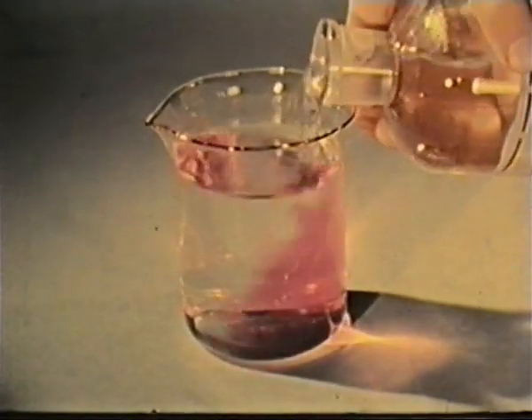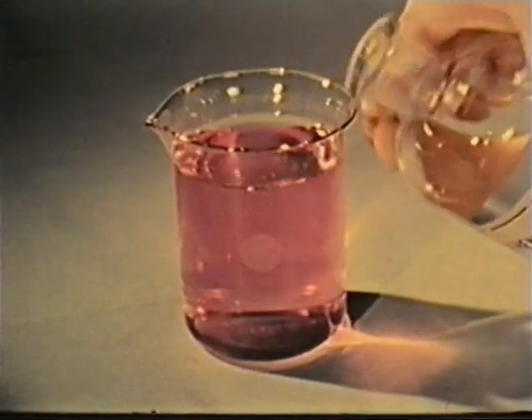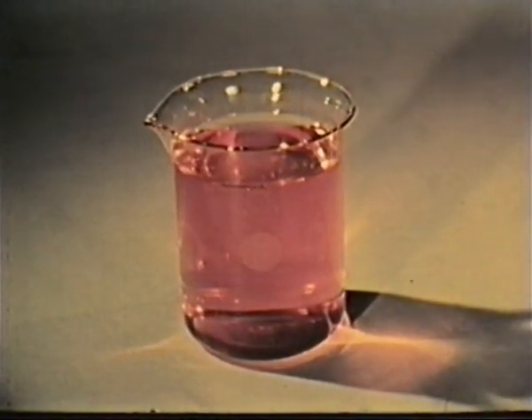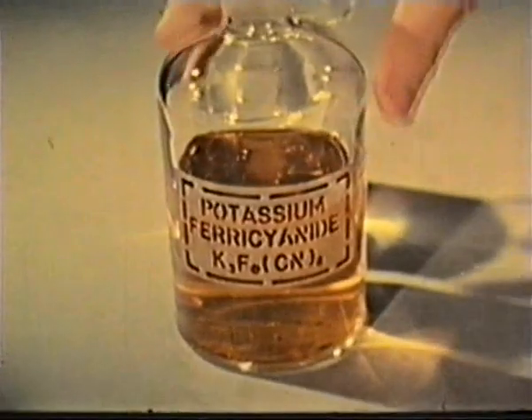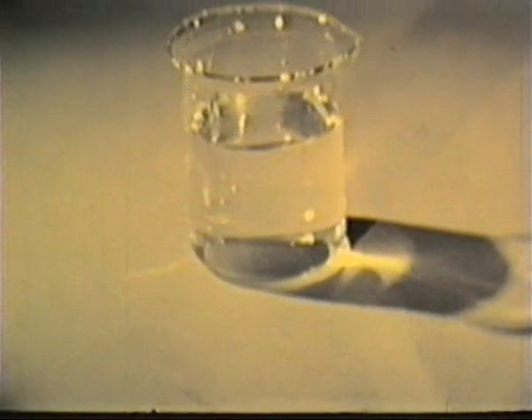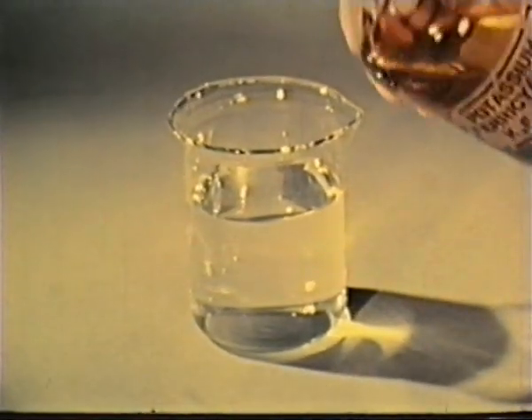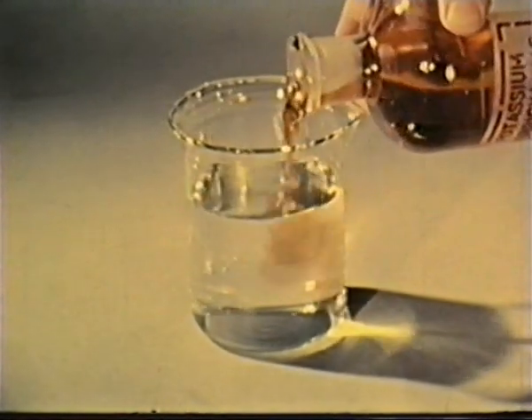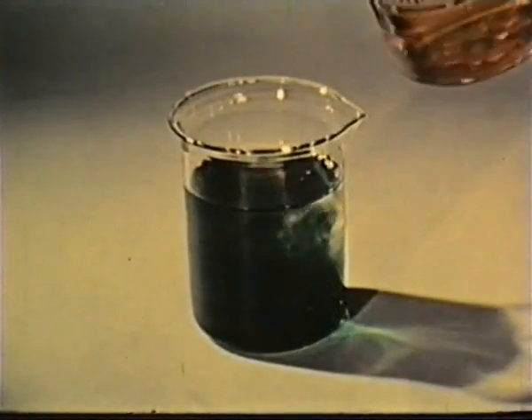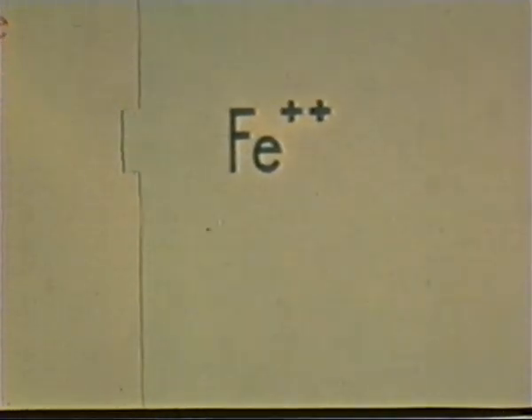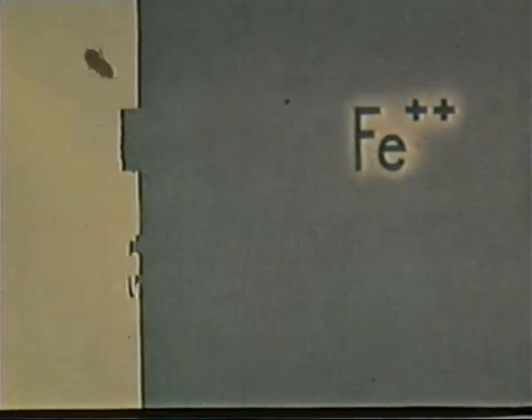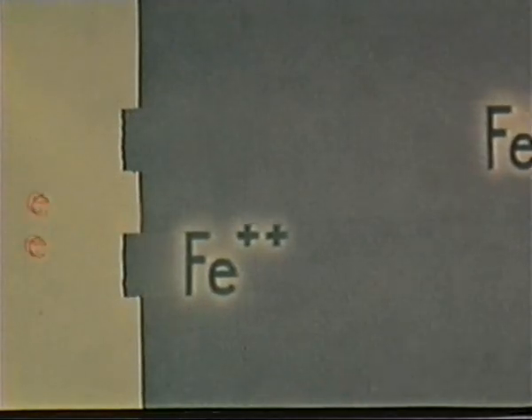Phenolphthalein is a well-known indicator which develops a red color when the concentration of hydroxyl ions is increased to the point where the solution becomes alkaline. Therefore, if phenolphthalein turns red as corrosion proceeds, it will detect the existence of a cathode and reveal where it is. Similarly, potassium ferricyanide is a reagent which produces a blue color by reaction with ferrous ions formed at anodic areas when iron corrodes. The appearance of this blue color, therefore, demonstrates the existence and location of anodes on iron.